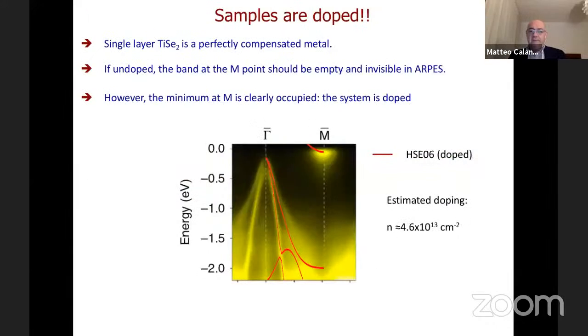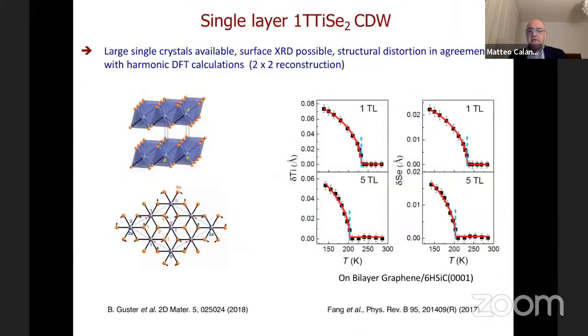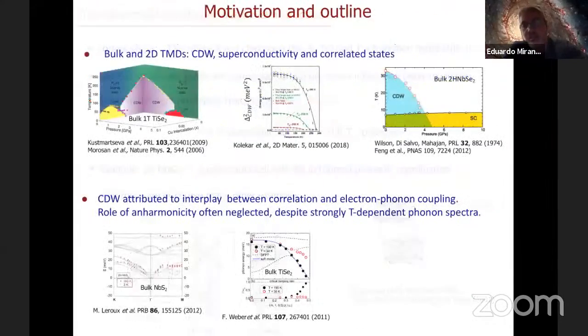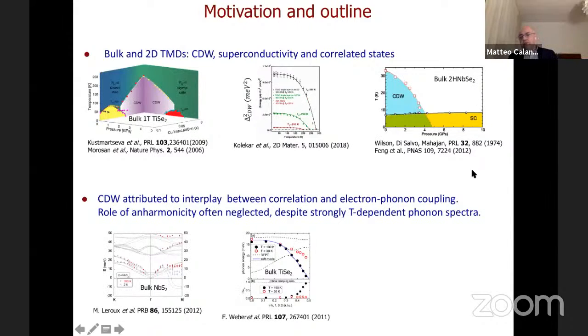Yeah, of course. From the phase diagram, it looks like superconductivity always appears at the point where the charge density wave goes to zero or disappears. Not always. It depends strongly on the system. So this is a very good question indeed. One case is titanium diselenide. So for example, this is the bulk.